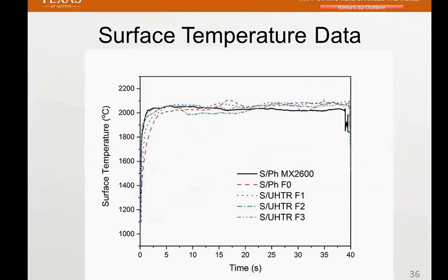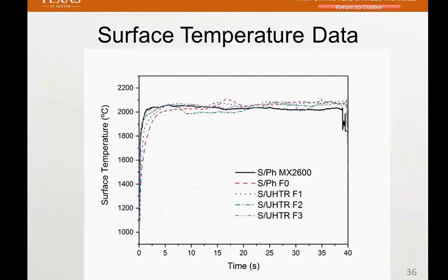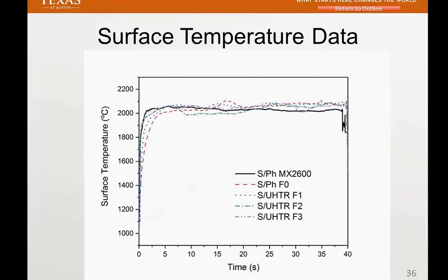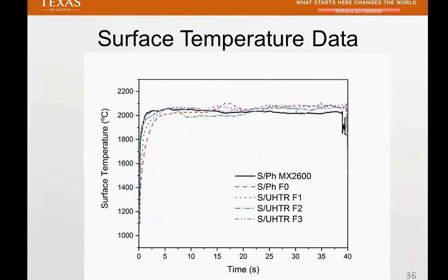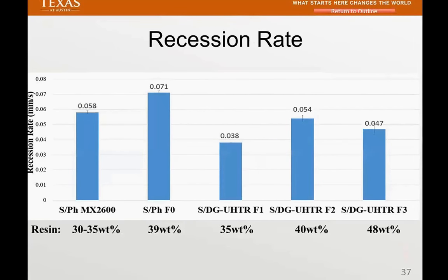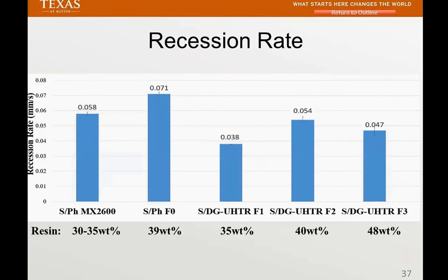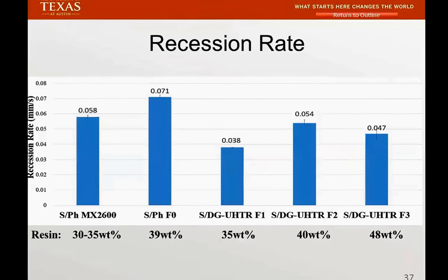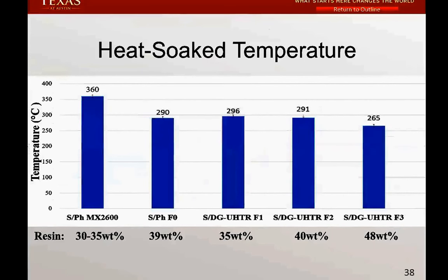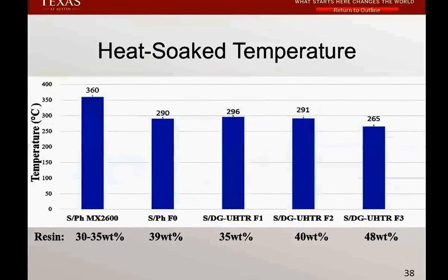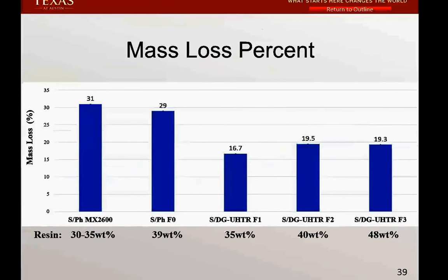Then we measure the surface temperature, which is similar to what we did for the NASA project. We have a two color pyrometer, so emissivity is not an issue. They cancel each other out, and this is what you see, very high temperature, 2,000 degrees C during the test. And this is recession rate. Lower is better. Basically, you can see that this is the best active formulation we have compared with the industry standard. Heat soak temperatures are all lower than the industry standard. We also measure the mass loss.